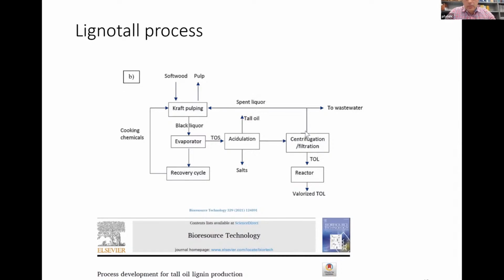And the current process everywhere is that after getting the tall oil out, they send back the remaining salt and lignin and so on to evaporators and then follow the kraft process. So we did some tests, and what we wanted to see is if this lignin after this acidulation is structurally different from the lignin in here in black liquor.